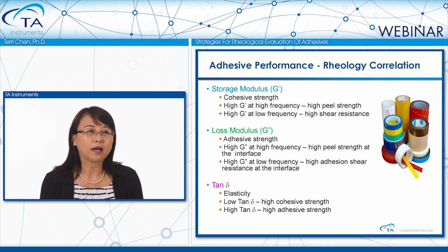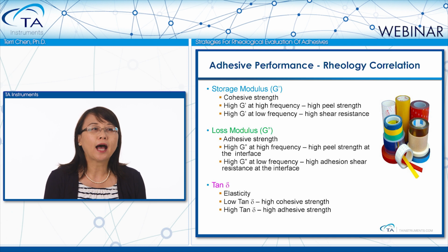A higher G prime at high frequency, which correlates to high shear, indicates high peel strength. A high G prime at low frequency, which correlates to a long time, indicates a good cohesive shear resistance.